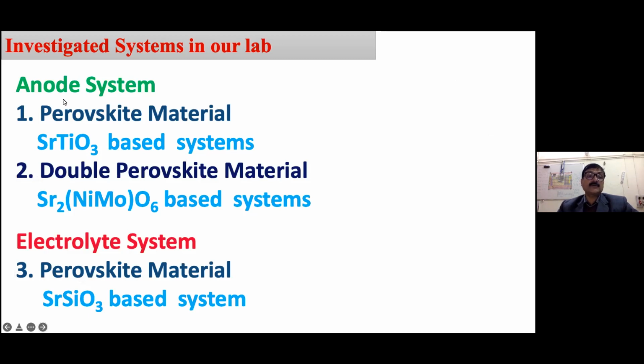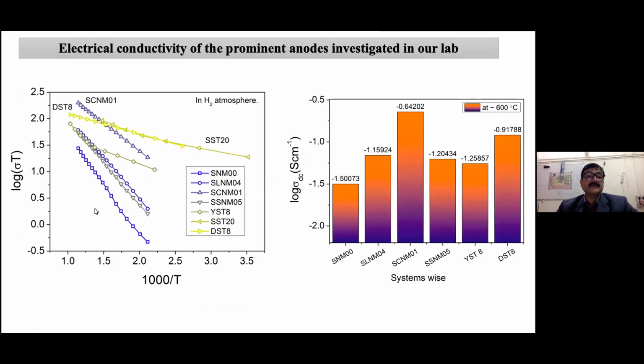In our lab we have worked on perovskite materials: the strontium titanate based system, double perovskite materials, and the strontium silicate SrSiO3 based system. These are a few works from our labs. This is the range of conductivity shown. I think the calcium doped material shows the highest conductivity, and it also has very good durability. We measured it in a hydrogen atmosphere, and you can see the data shown here. So good conductivity was reported from our lab in different materials.